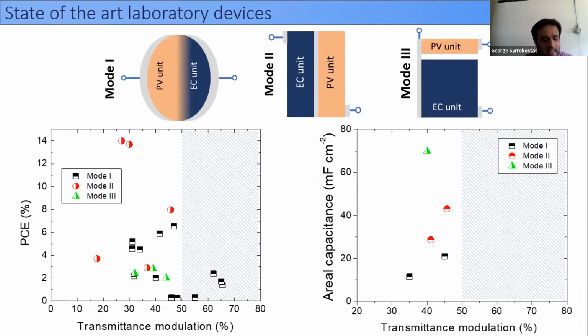But to continue with the state of the art and the current state of photoelectrochromic windows, of course, there are different indicators to describe their performance. Here, I have chosen to show you two graphs. On the left side, there is a graph of the transmittance modulation with respect to the photoconversion efficiency of these devices. We see that today we have devices with photoconversion efficiency up to 14%, but in this case, the optical modulation is very low. Also, we have many devices in this area, and also we have devices that have a photoconversion efficiency of 2 or 3%, but they have a transmittance modulation above 50%. That is comparable to a commercial electrochromic window that has at least 50%.